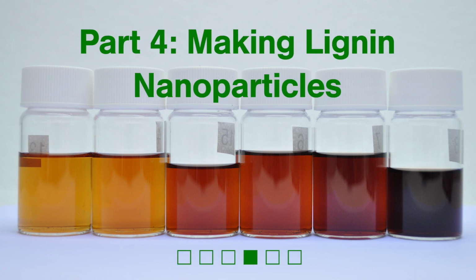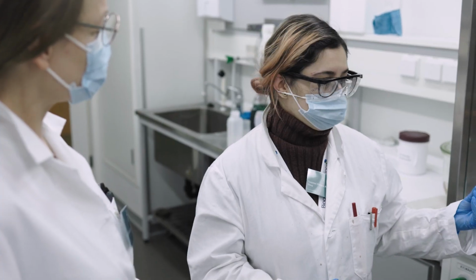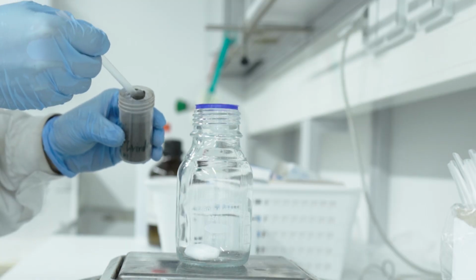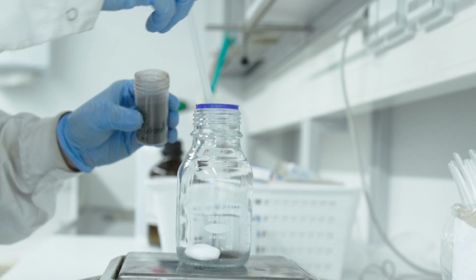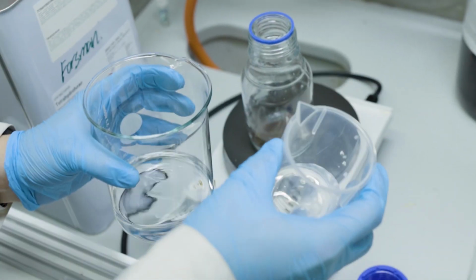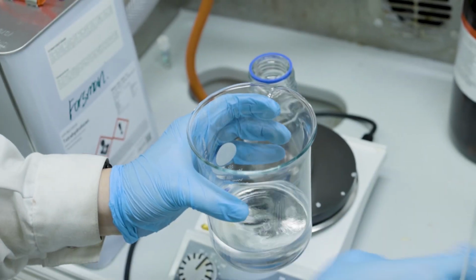The hardwood biorefinery lignin received from Avantium is first purified to remove the processing residues and then dissolved into the binary solvent. This binary solvent consists of an organic solvent and a small amount of water.